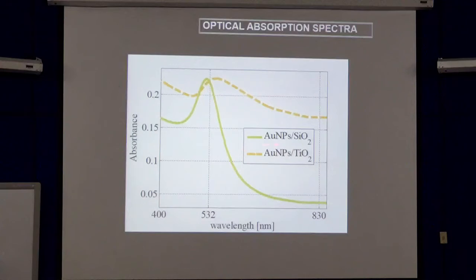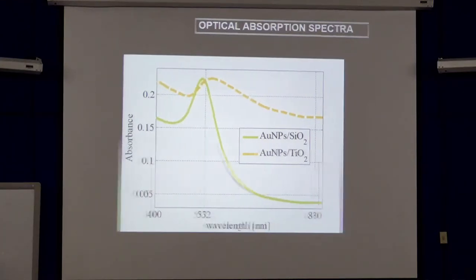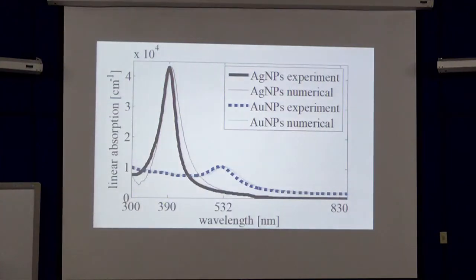In this case, this is silica, and the other one is titanium, the surrounding of the same nanoparticle. So if you can change the induced refraction of light from positive to negative, you can accelerate or you can delay the propagation of light by the same sample. So you can put like a sandwich, and then eventually control the different speeds of the light with refraction. Or you can use different samples.